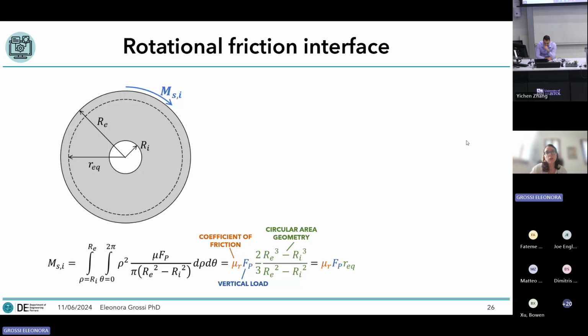starts to rotate not when reaching a sliding force, but a sliding moment. And this sliding moment is a function of the coefficient of friction, the vertical load, but also of the geometry of this area. You can see here that it's a function of the outer and inner radius of this area. So I simplified this formulation and computed an equivalent radius that I wrote as R_eq.